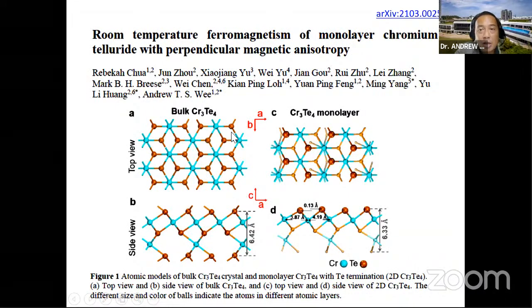And when we thin it down to a monolayer, you actually have vacancies in this row of tellurium. And in fact, from XPS, which I'll show later, the ratio is more 1:2. So in effect, the monolayer is more like chromium ditelluride, right? So this is our postulated structure based on the data, which I'll show you.